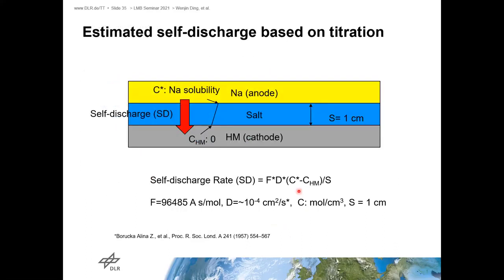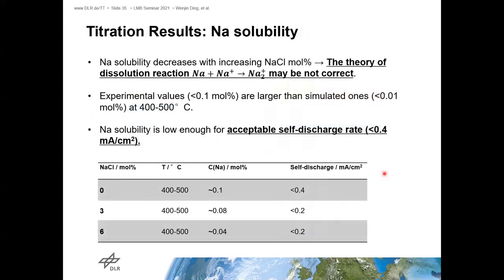So from the sodium solubility, we can use this simple model to calculate the self-discharge rate using this equation. From the concentration gradient, we can calculate this self-discharge rate, and we use the value from the literature here. And our titration result shows that, as shown here, when the solubility of sodium chloride in the salt increases, that means there is more sodium chloride inside. In this temperature range, we find out the sodium solubility decreases.